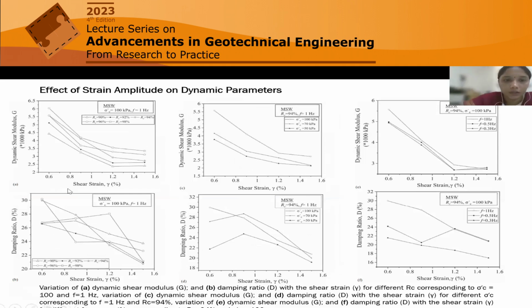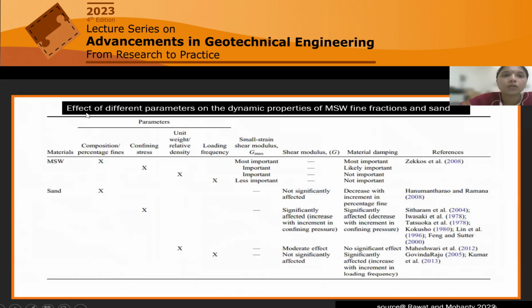This shows the effect of shear strain amplitude. Here you can see with the increase in shear strain, meaning cyclic strain, the dynamic shear modulus is decreasing, for all the cases, meaning varying relative compaction, confining pressure and frequency. And for damping ratio, here also we are getting a decreasing trend, but not a systematic one, a random trend. So this slide shows the effect of different parameters on dynamic properties of MSW fines, and the fine fractions of sand, meaning soil, we have also compared.